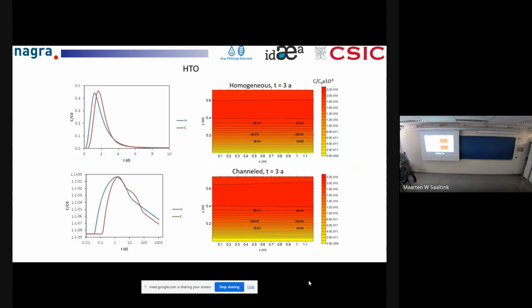These are parameters I already discussed, and so these are the results again. Pulse injection during 20 hours. This is the case for tritium. You have the breakthrough curves at the extraction borehole, relative concentrations, in linear scale and log scale. And this is the distribution of the tracer after 3 years. Basically the highest number is a relative concentration of something like 10 to the minus 4.